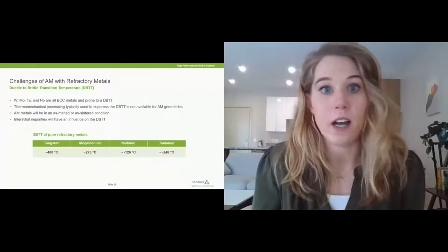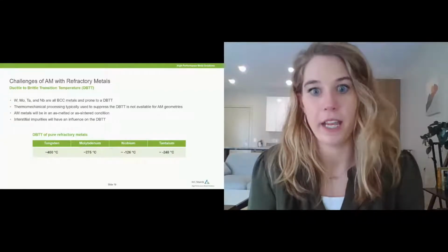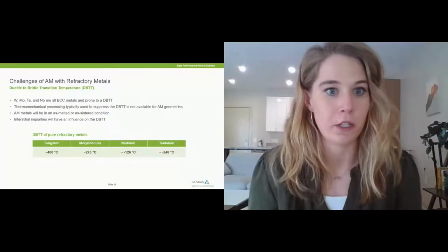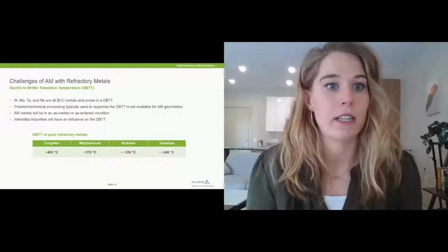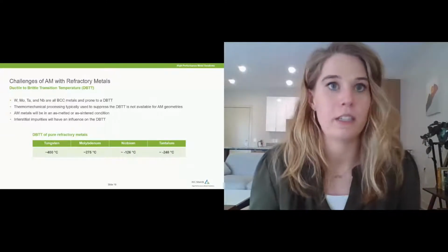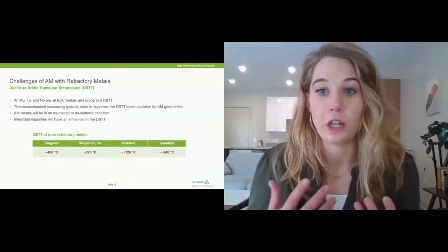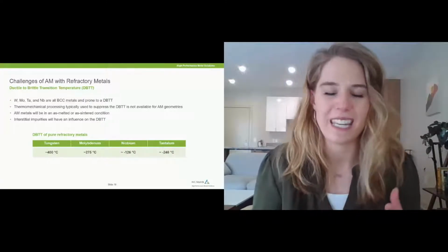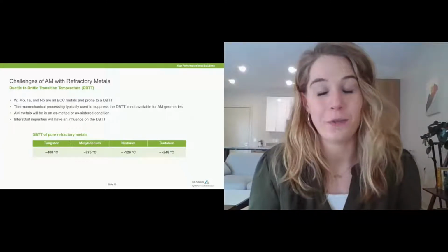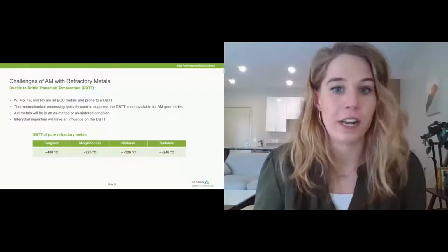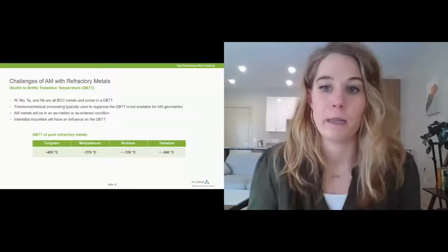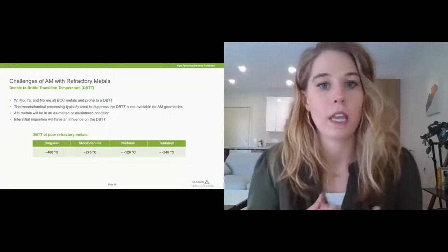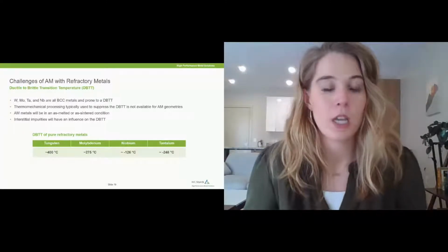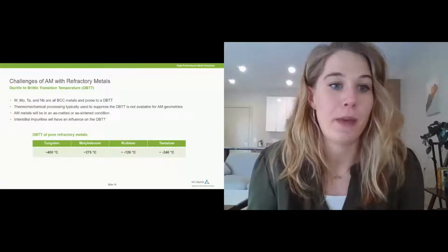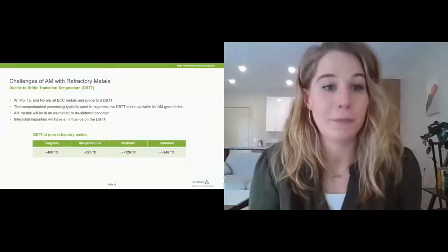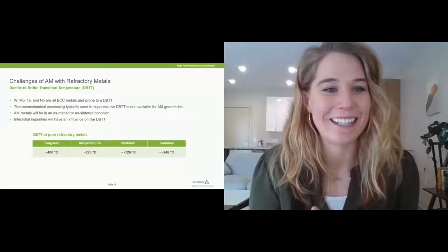So speaking specifically about tungsten, tungsten is one of those metals that has a very high ductile to brittle transformation temperature. Usually in traditional processing, thermomechanical processing such as rolling and forging is used to decrease that transformation temperature and make it easier to work with. But unfortunately, with additive manufacturing, we're printing at near net shape. So we don't have that option to mechanically process or cold work or hot work these materials to make them more workable. So one thing to consider is that all of these AM metals will be in as-melted or as-sintered condition.